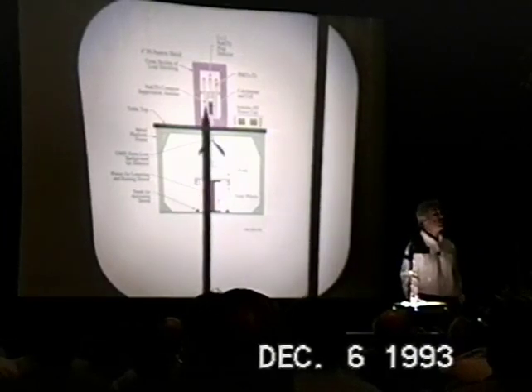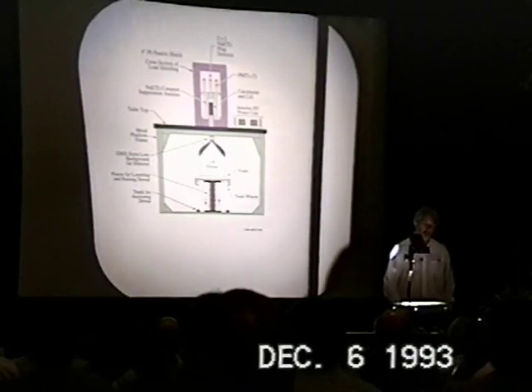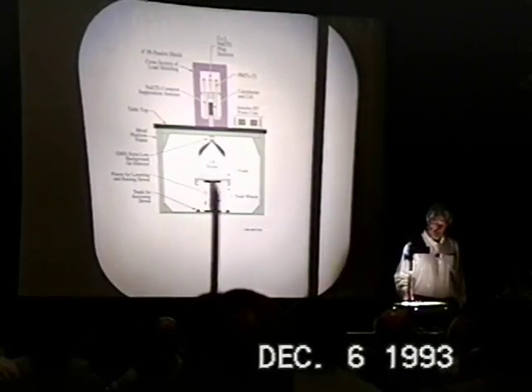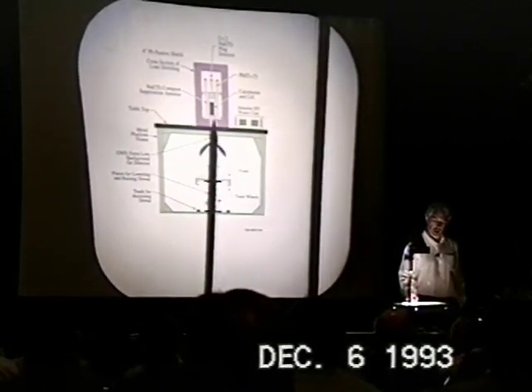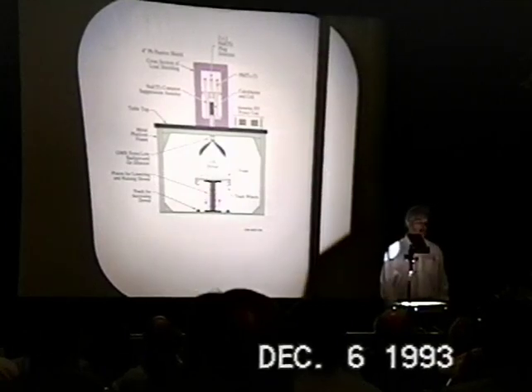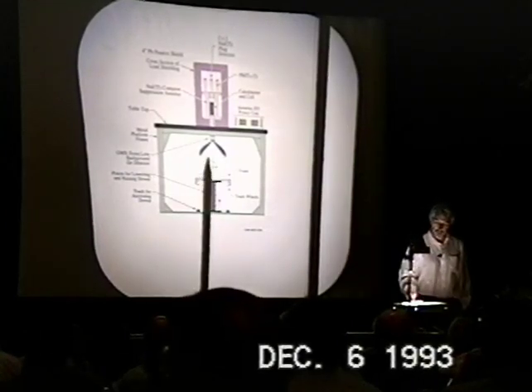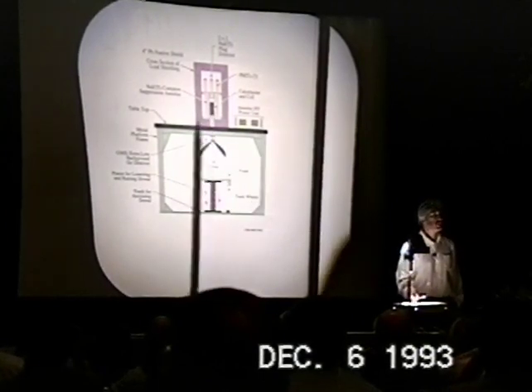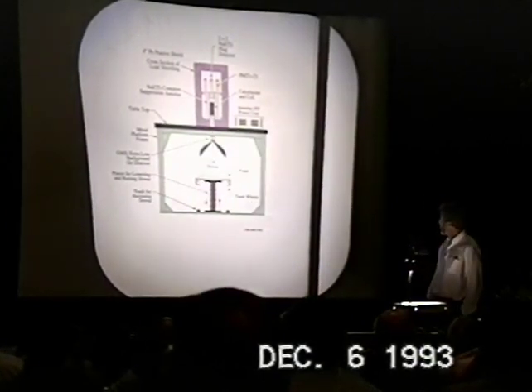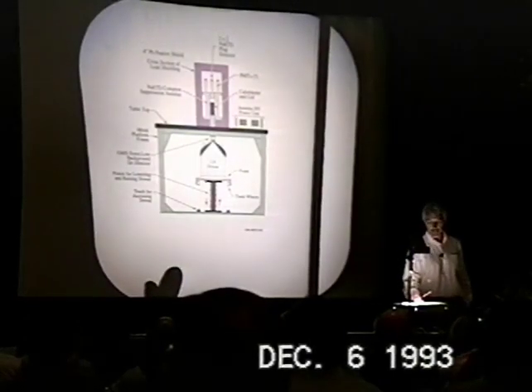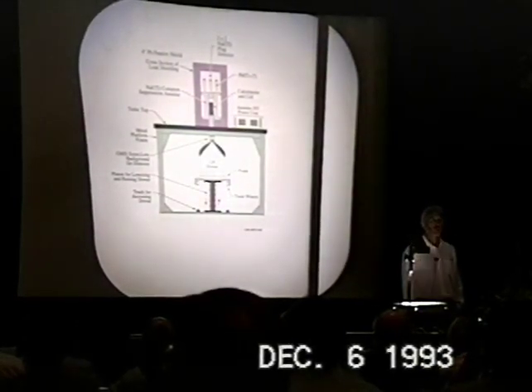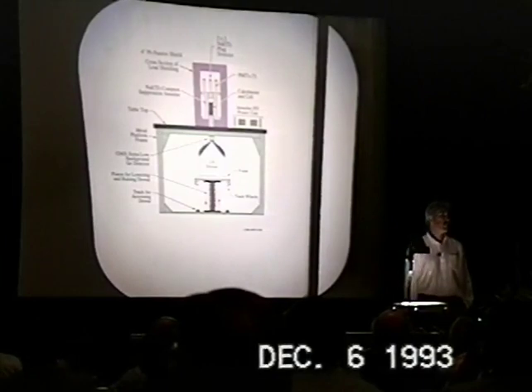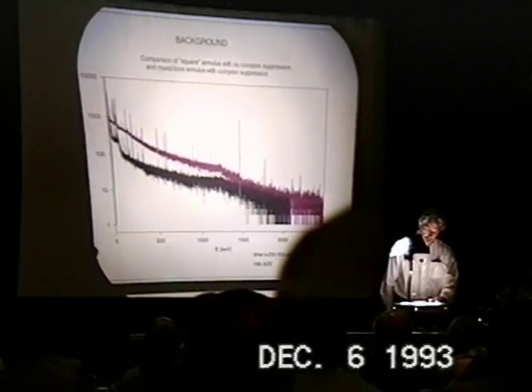inside of which is a sodium iodide Compton suppression annulus, into which, inserted from the bottom, is a germanium, liquid nitrogen-filled germanium detector, an ultra-low background detector. And the red space here is the working space for a calorimeter. There is a calorimeter running inside the system presently. We have not, unfortunately, as yet, either obtained adequate loading or excess heat production in the system. We've beaten the background down to a pretty decent level, in fact.